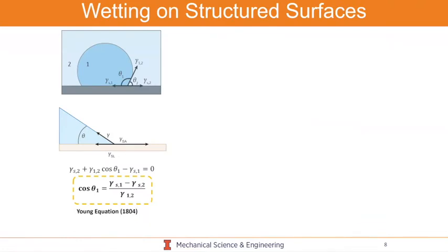So, now what happens when we add structure to the surface? In this case, if you look at water wetting a surface, the contact angle you make with the surface, this theta 1 here, is really dictated by the force balance at the contact line. So you have your liquid-vapor surface tension, which is the thermophysical property I mentioned before of the liquid. But then you also have surface tensions or surface energies between the water and the solid and the vapor. And that really dictates this force balance, the three-phase contact line. And that's hence why there's a famous equation called Young's equation by a European scientist named Thomas Young, who in 1804 wrote this down for a smooth surface.